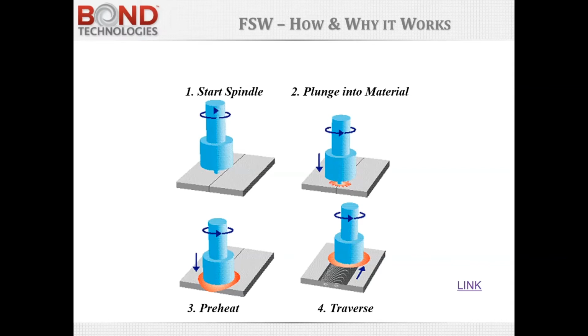As the shoulder engages, it's a much larger surface, so the torque goes up, the amount of heat being generated goes up significantly, and the region around this pin tool becomes plastic. Now it's below the melt point of the material, so picture toothpaste, if you will. It's about that level of flow stress and shear strength. As soon as the region below the pin is preheated, the pin traverses along the joint.